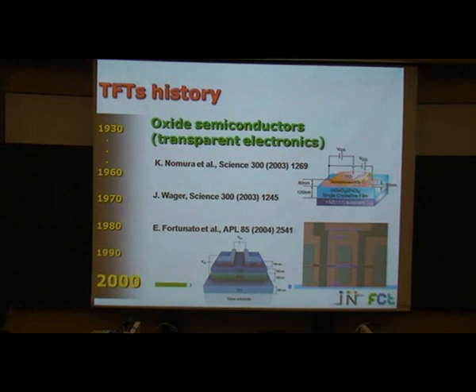And more recently, after 2000, it was proposed by Professor Hosono at the TIT laboratories in Japan a device where we can use an oxide semiconductor as the semiconductor. So we can substitute the traditional semiconductor with an oxide material. In this report, he uses a monocrystalline complex oxide with indium, gallium and zinc, but the temperature for growing this monocrystalline film was around 900 degrees. So if you are looking to use this type of device, for example, for large panels or for the industry, this is also a problem.